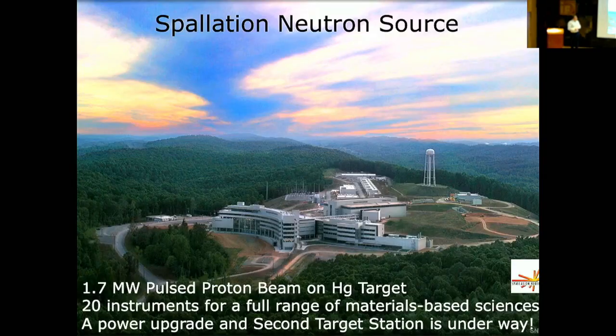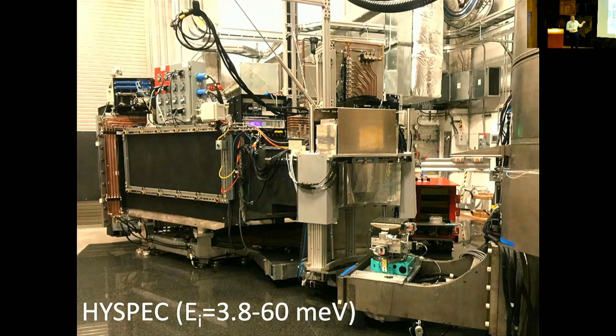So we're using the facility. We're using this instrument, which looks very complicated. But all I want to point out is that this instrument can measure scattering into a horizontal plane. The neutrons come in here, and then they scatter into a big detector back here. But they can also reach a position-sensitive detector, so I keep track of the vertical wave vector transfer as well.